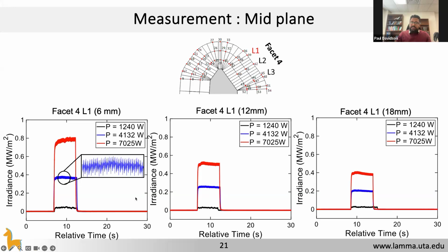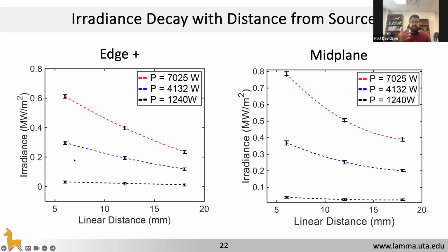And then we average out the incident radiation over a time period of about 5 seconds to get a reasonably good result. And then what we can do is interrogate that profile and see how the incident radiation changes with respect to, say, linear distance and at different locations of the quartz itself. So here I'm showing you how the incident radiation changes. And as one would expect, as the linear distance from the quartz itself increases, the value decreases.